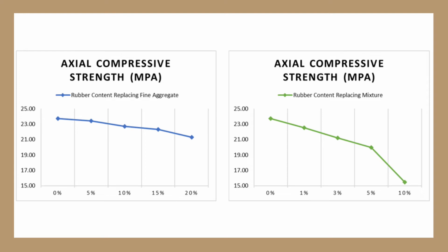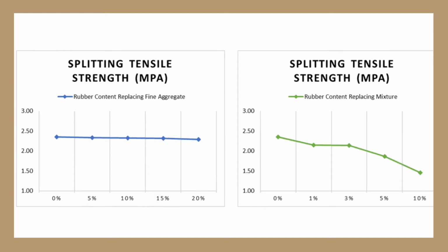Here are the mechanical properties of the modified concrete specimen from the study of Yu et al. in 2016. The compressive strength of crumb rubber concrete was shown to be lower than the control concrete after the curing process of 28 days. Thus, replacing the fine aggregates with crumb rubber is better than incorporating the change in the mixture. Despite having a lower compressive strength than the control concrete, 20% replacement of fine aggregates still satisfies the requirement of C30 concrete. For the splitting tensile strength, axial compressive strength, and modulus of elasticity, an increase in rubber content results in a decrease for each mechanical property.